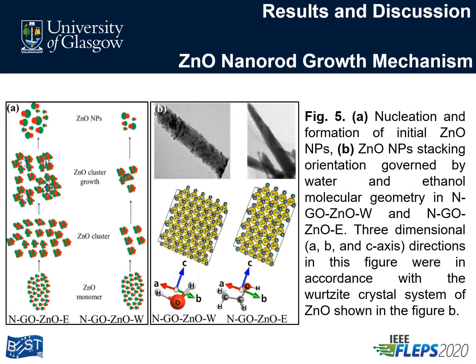After the formation of initial zinc oxide monomer, the nucleation threshold started to build up depending on the rate of supersaturation, which in turn is dependent on the solubility of zinc oxide in the solvent. The solubility of any monomer in a chemical system is directly proportional to the dielectric constant of the solvent.